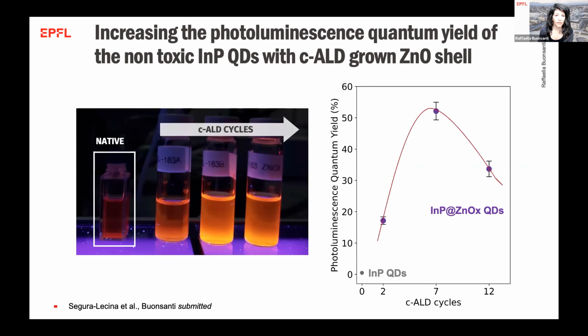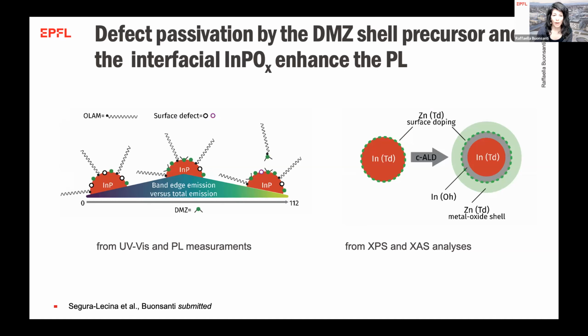More recently, we also demonstrated that as we start growing this amorphous zinc oxide shell around indium phosphide, we can also increase the photoluminescence quantum yield compared to the as-synthesized quantum dots, which we explained via some defect passivation on the surface by the DMZ, which is the precursor of the zinc oxide shell, some defect passivation on the indium phosphide, as well as some interfacial oxidation developing between the indium phosphide and the zinc oxide shell.